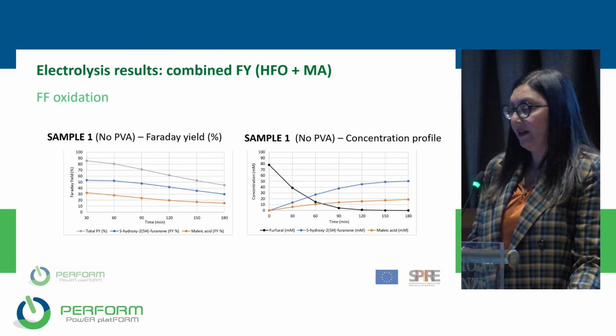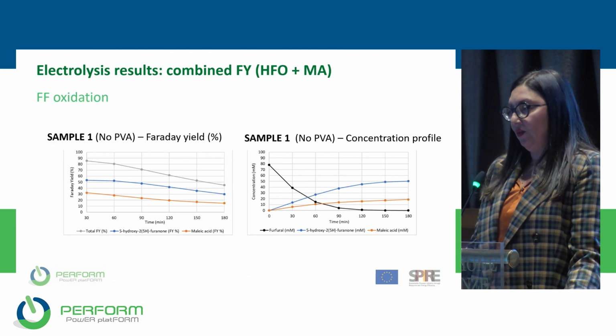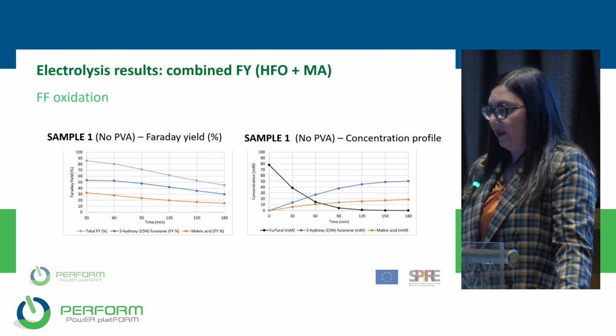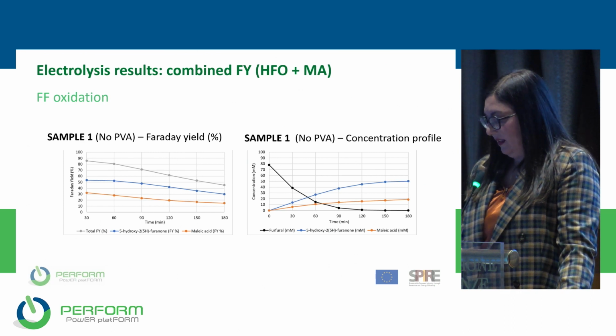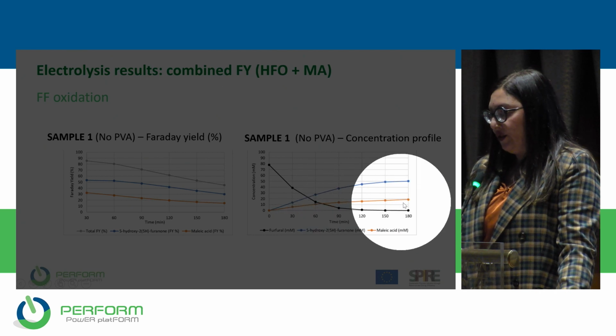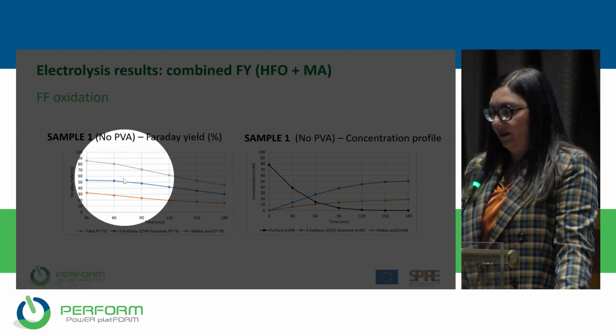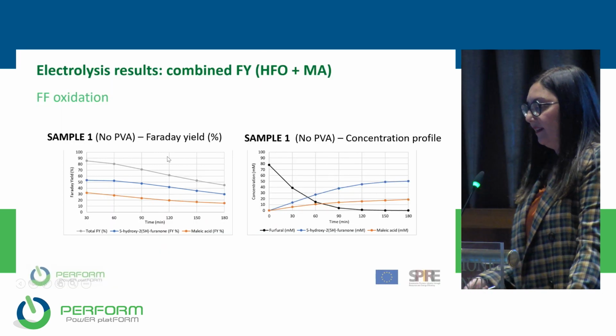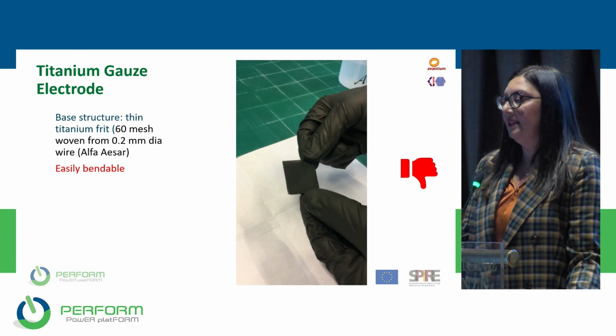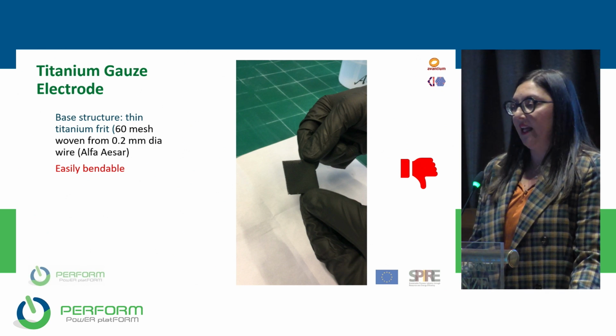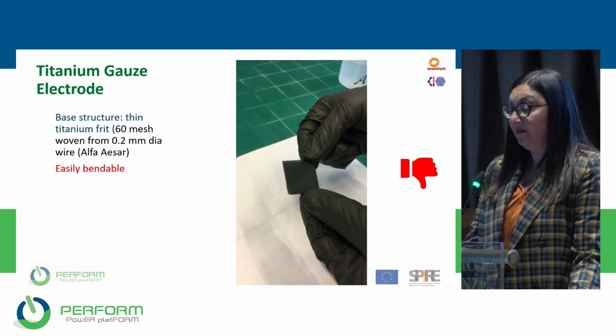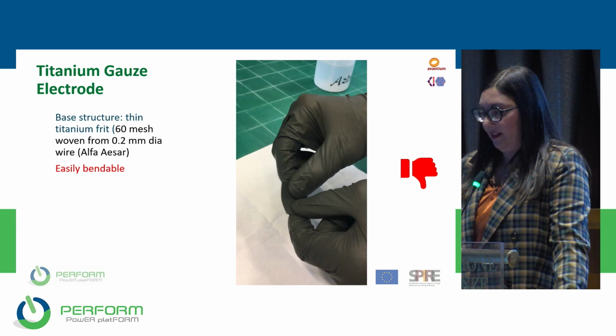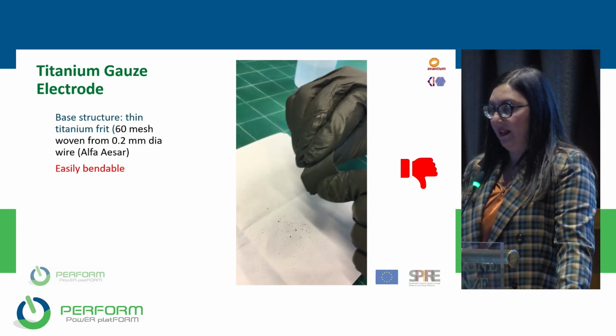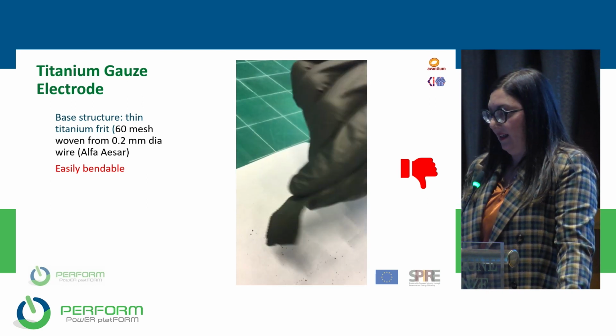The results are reported as combined Faraday yield because there are two products, HFO and the target molecule maleic acid. And you can also see the concentration profile and the Faraday yield of both maleic acid and HFO, and the total combined Faradaic efficiency in gray in this graph. But this first material prepared was not mechanically stable. In fact, you can see that it is easily bendable, and so it is not suitable for industrial electrochemical application.